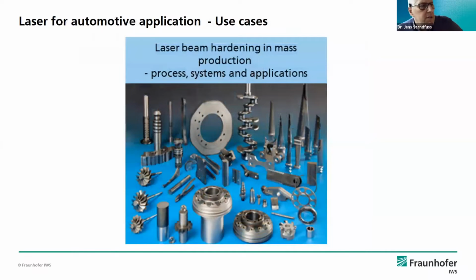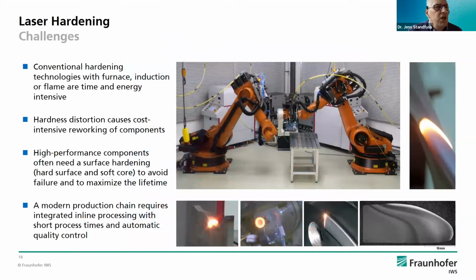This is the first application: laser beam hardening. What is the challenge for hardening? Conventional hardening technology using furnaces, induction or flame hardening is time and energy consuming. And the distortion is directly connected to the energy you put into the part, and that's why laser hardening offers you a good thing, because you can minimize the heat input and you can integrate it quite easily in an existing process line because it's quite fast and you have short process time, and we can also offer automatic quality control.